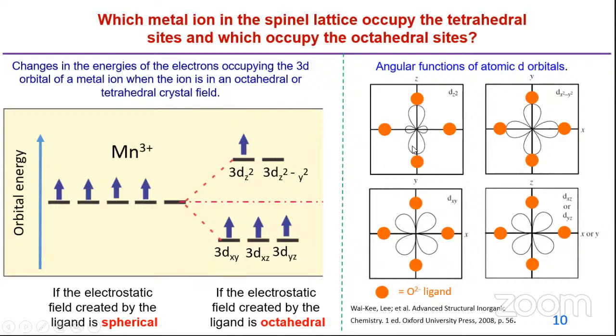If the orbitals and the electrons from the ligands stay in the same line, meaning the electrons from the ligand and the orbital are close, which is the case for the 3d z² and 3d x²-y² states, these orbitals and the ligand electrons are very close, so they will feel a strong electrostatic repulsion, which makes their energy state higher, so they will go up.